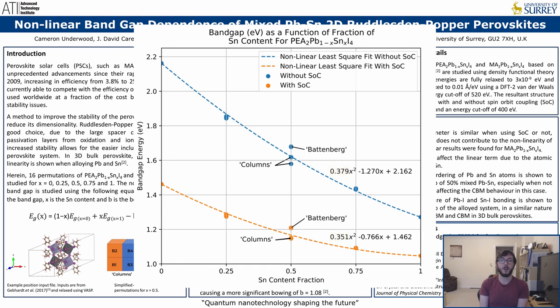We can see in this graph that while spin-orbit coupling strongly affects the linear term, it does not affect the bowing parameters significantly. However, we do find that the conduction band minimum behavior, such as effective electron masses, is strongly dependent on spin-orbit coupling, so this should be included.